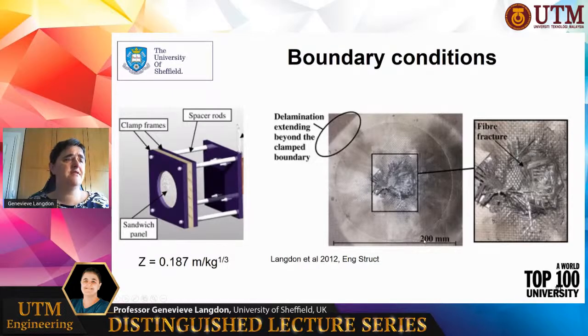Again, this is a glass fiber panel, and you can see here that in this particular test, rather than clamping it tight around the edge of the circle, what we did was just put four bolts around the corners to have a look at how that changed things. And we were able to get rid of the premature indentation failure. But what it did do is you see the delamination failure goes far beyond the boundary, which perhaps is to be expected as the material deforms outwards. And in the center region there, you see extensive fiber fracture.